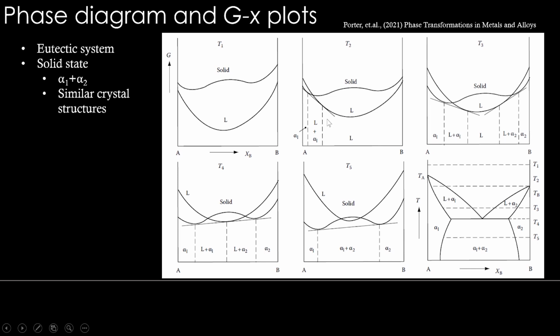Then at temperature T3 here, something similar to what we saw in the previous slide, where we have two tie line information coming, one from here to here and one more from here to here. Therefore, liquid should be plunging into the solid state Gibbs energy, so that you get these two common tangents. You can translate this composition information here and read the tie line. So if you feel it's slightly difficult to understand, pause, see carefully how these things translate to one another.